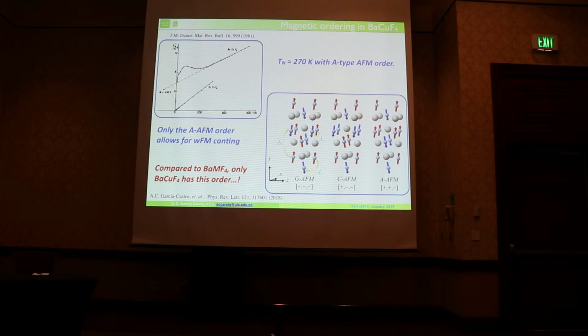And what's going on here? We can have these three different magnetic orderings for the unit cell. In the layer we have two interactions. We can have this one, which we call JC, and this one, which we call JA, and the interaction between the layers. We can have full antiferromagnetic interactions. This one we call G. For this one we have a ferromagnetic interaction along the x-axis, but antiferromagnetic interaction between this one and this one. And the other one is where we have the same ordering in all of the layers.